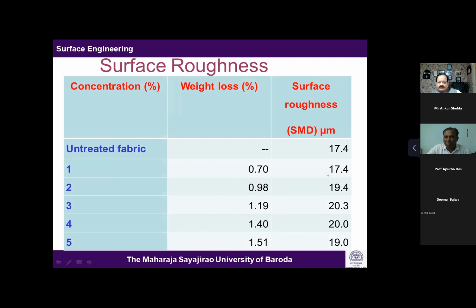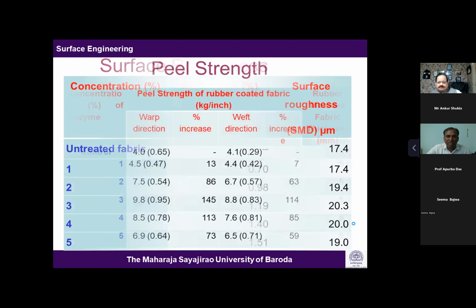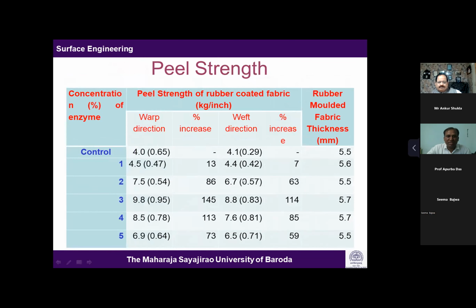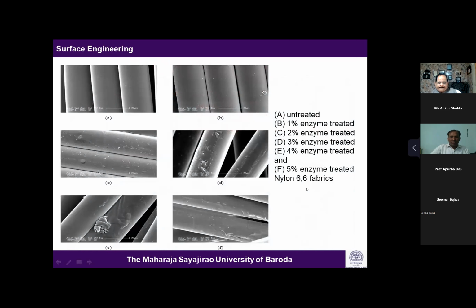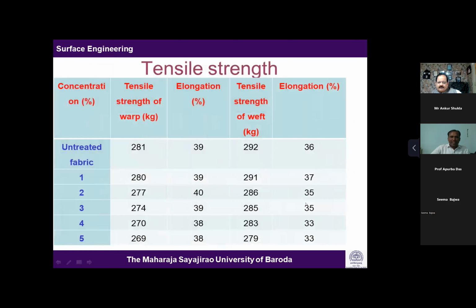Again, surface roughness is found to increase, and we found an optimal value at 4, and then there is a slight decline. The peel strength again increases with the treatment. These are the SEM pictures of the treated nylon. The tensile strength again shows a slight decrease in this enzyme treatment, maybe because of the same bulk effect.